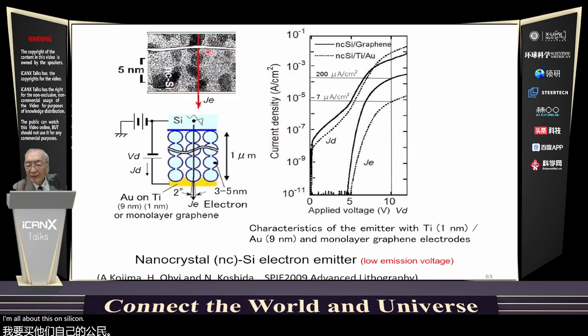By electrochemical oxidation in ethylene glycol, a thin oxide film is formed on the surface of the nanocrystalline silicon particles. Ballistic electrons accelerated through cascaded tunnel junctions of the oxidized silicon particles are emitted through a thin gold or monolayer graphene electrode by applying a low voltage of 10 volts. The low voltage is indispensable for the active matrix driver LSI.